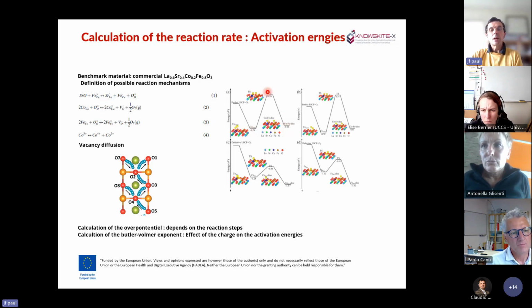But doing that, you will have an idea of the transition state, and once you have the transition state, you can characterize it by computing frequencies, and you can estimate the activation energy. And this can be done on the surface, or this can be done inside the solid. Here it's for the activation of O2, and here it's for the diffusion of the oxygen inside the system. Some important points also to add for this type of calculation.